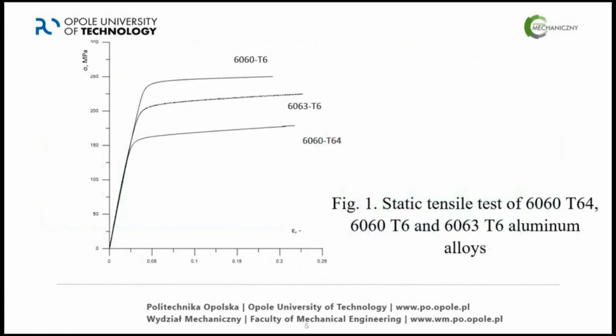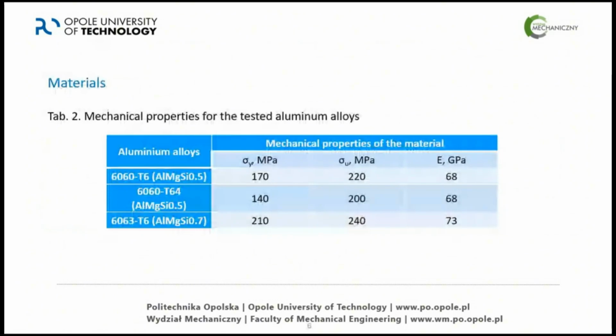We see that the higher strength is for material 6060 in T6, and the lower is for 6060 T64. But it's a problem because when you make windows or doors, we have big deformation. When we use 6060 T6, the static strength is higher, but the aluminum sometimes breaks. So sometimes factories use the T64 treatment, but the static strength is less. So the engineer must look at what kind of material to use in the real construction. The mechanical properties of these tested aluminum alloys are very close to the standard for this material.